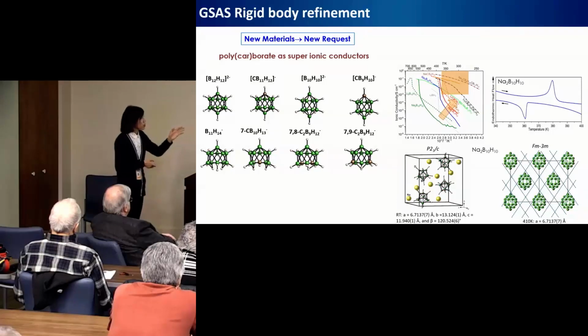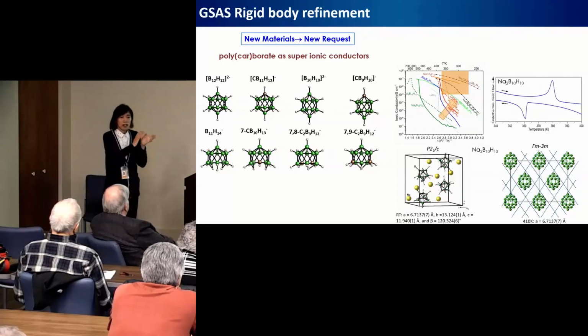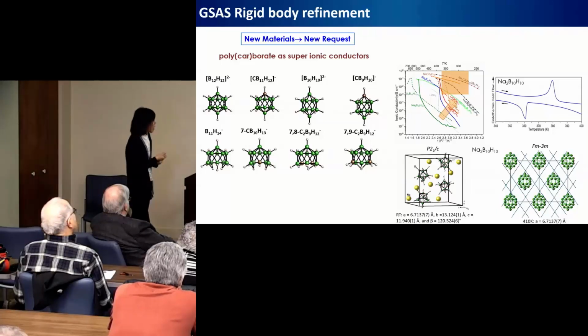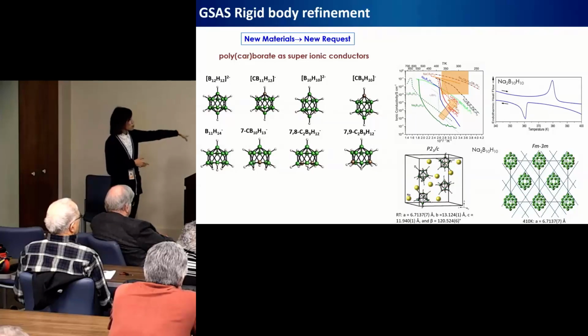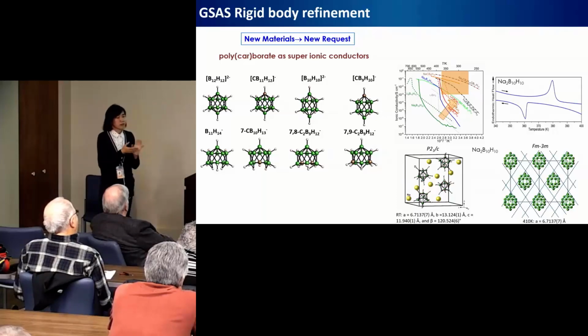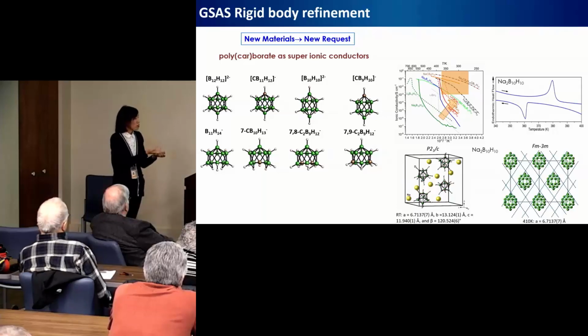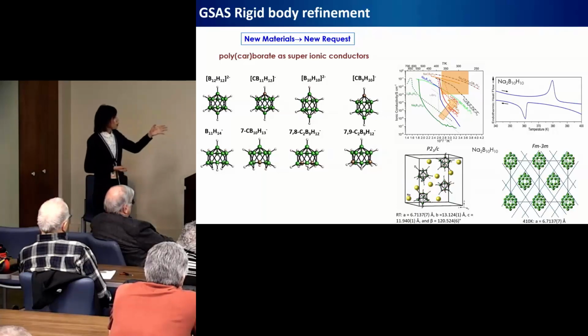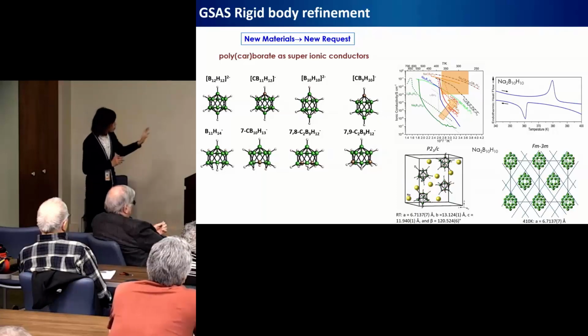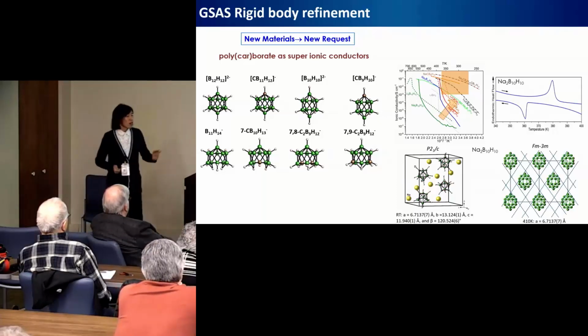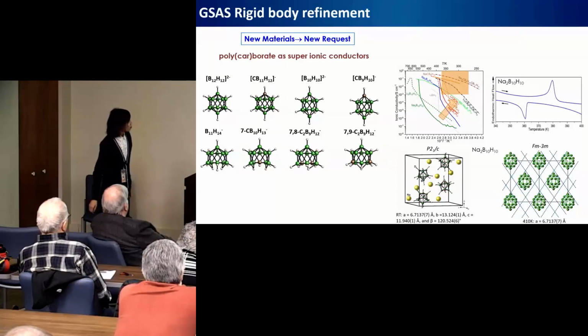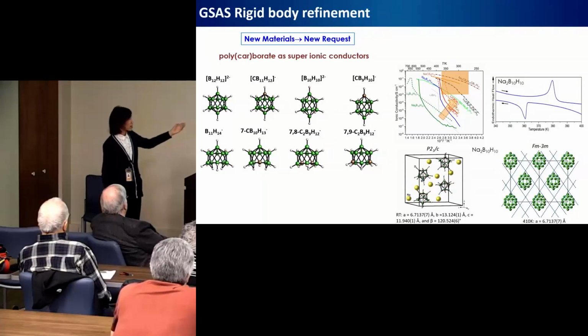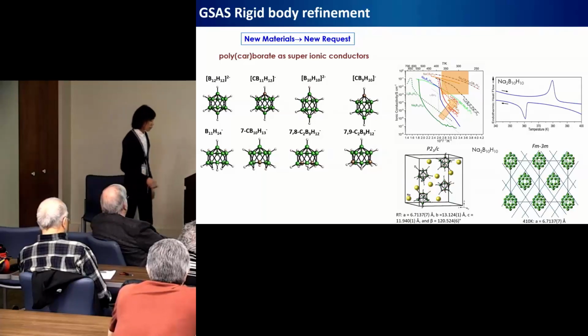Below the phase transition temperature, those polyhedral anions have a definite orientation, so we call it an ordered structure. For all those compounds, the high-temperature disordered phases have more or less similar structures, depending only on the packing pattern, BCC or FCC or even HCP. But at low temperature, they have different ordered structures because of the different size, shape, and polarizability of those anions. So we want to know the structure of those compounds at low temperature. Unfortunately, we always have powder samples and cannot do single crystal, and also, as you can see, these are boron-rich materials. So again, we have to rely on X-ray powder diffraction data.